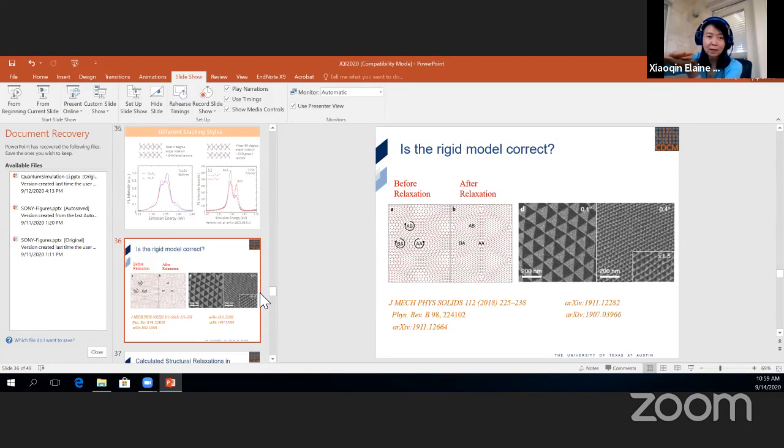So with those, you can create supercells that are a few hundred nanometers large. You can control the angle very precisely. So that perhaps is a better way if we're looking for a quantum emitter array. That could be a better way to go forward. Our existing work was taken from two completely different monolayers. Then we don't have such a nice angle alignment. Then we're not in this regime of lattice reconstruction.